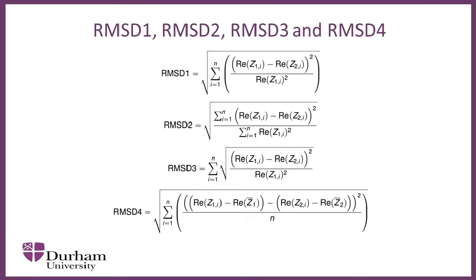So the figures show the RMSD value obtained for each transducer for each of the damage conditions. As the RMSD is a measure of the damage, the higher the value, the more severe the damage is. The damage under condition 1 and condition 2 was a 2 mm diameter hole and a 4 mm diameter hole at x equals 0 and theta equals 90. It can be seen that the damage metrics obtained under condition 2 are in general higher than those obtained under condition 1. Under condition 3, two 5 mm holes were drilled, one at x equals 0 mm, theta equals 90, and one at x equals 20 mm, theta equals 90.